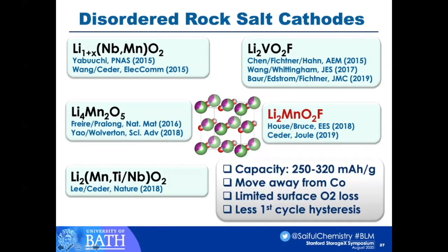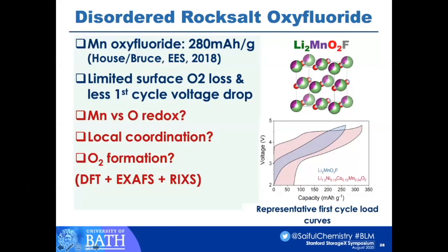So what is it about these systems? The capacity can be really high, 250 to 320 milliampere hours per gram. So we're touching towards 1,000 in terms of watt hours per kilogram. So we're moving away from cobalt. There's limited surface oxygen loss, and there's less first cycle hysteresis in many of these systems. So I'm going to focus on some recent work we've been doing on the disordered rock salt oxyfluoride. This has a capacity of about 280 milliampere hours per gram, limited surface oxygen loss, and less first cycle voltage drop, which you can see in the schematic on the bottom right.